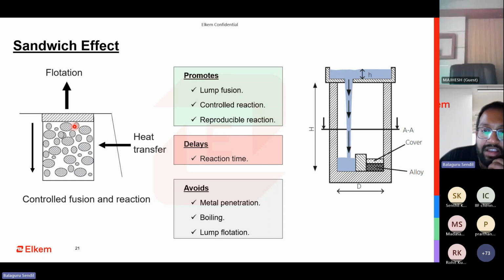This is the basic L by D that we discussed here. I have put a formula here. Basically, this D is the hole here. So the tundish you are using, which is well and good. In the tundish, you have a bottom hole. So this hole has to have a particular diameter. That diameter needs to be balanced.